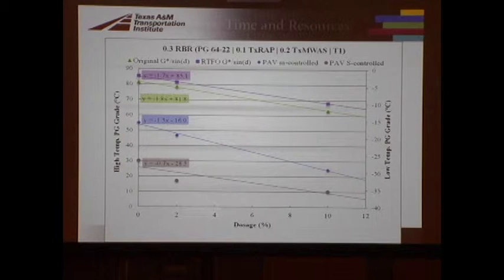So the way that the first trial of restoring the PG low temperature grade works, what we do is we come along here. So this is controlled by M control, right? The M value is saying it's a minus 15. And the S value is saying it's a minus 26. So it's an M controlled when we're over here at 0% dosage. So we keep adding in dosage along a linear relationship, and everything that we've tested seems to be linear. So we're using a linear relationship. We feel fine about that. I don't know what would happen if you added 25%, but you're not going to add 25%, so it's okay. So at these dosage levels.